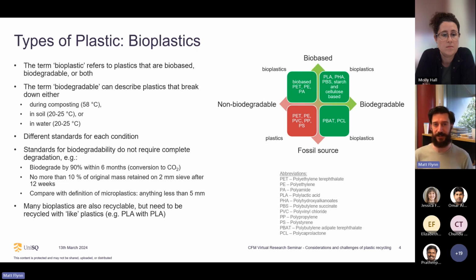So if you compare this to the definition of microplastics, which is any plastic particles less than 5mm, by definition, the biodegradation involves a step where you're generating microplastics. So this can be a problem if they're not biodegrading fully. You end up with just microplastics being generated in the environment. And as well, you can see the difference between 12 weeks, so roughly 3 months, versus 6 months. The composting facilities want to get through their product as quickly as possible and turn over as much stuff as rapidly as possible. So if they can get away with it, they're going to cut the times down shorter, and they might not have this biodegradation happening fully.